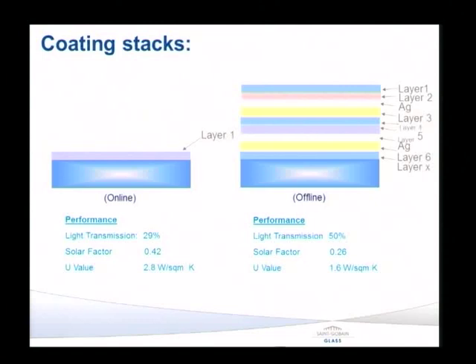Look at the performance of this glass. The desired quality of light transmission is much higher. The solar factor is much lower. In fact, you have about twice the amount of light coming in as compared to the heat, and the U value also reduces. So you get a much better performance by doing an offline coating.